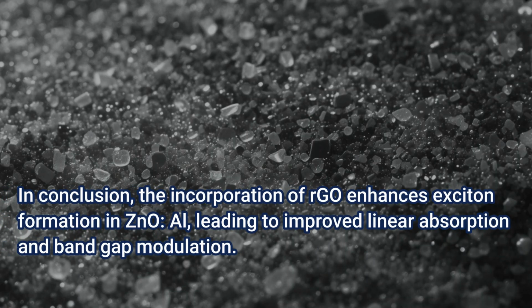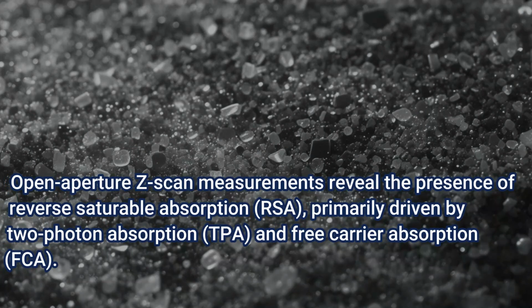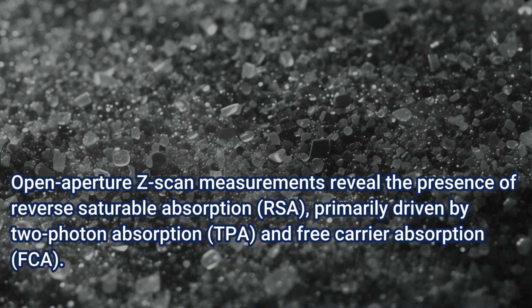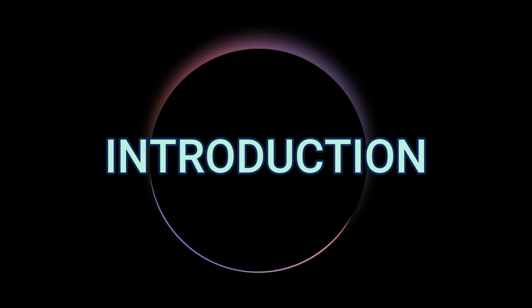In conclusion, the incorporation of rGO enhances exciton formation in AZO, leading to improved linear absorption and band gap modulation. Open aperture Z-scan measurements reveal the presence of reverse saturable absorption, RSA, primarily driven by two-photon absorption, TPA, and free carrier absorption, FCA. Introduction.